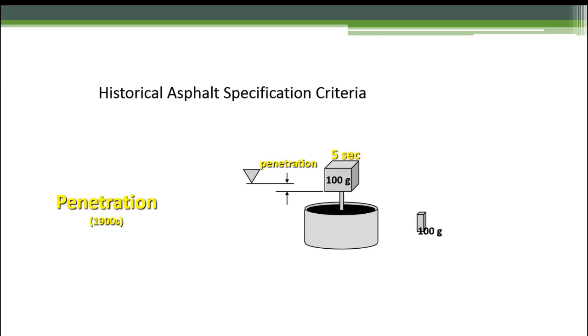And what's kind of interesting about this is that this is one of the older tests in AASHTO and ASTM, penetration grading of asphalt. Why room temperature? Well, you could test it any place across the United States. If you were in the middle of the Dakotas or middle of Wyoming, and you didn't have an oven to heat it up to a certain specified temperature, and even if you did, you didn't have a way of measuring that temperature. So it's kind of a room temperature test. 100 grams, that's fairly simple to weigh out. Probably a postal scale will do that.